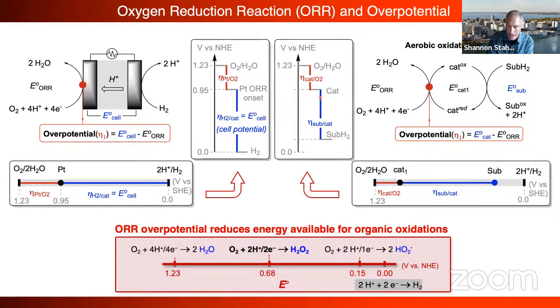In organic oxidation chemistry, it actually depends. And I hope the take-home message you take away is, at least conceptually, thinking about this overpotential for O2 reduction, overpotential for substrate oxidation. You may want a catalyst that sits down here very close to the substrate oxidation potential, so that you have a very exquisitely tuned catalyst with very good functional group compatibility. You may not want to hit it with a sledgehammer in this way, with the large driving force. And so sometimes you want to expand the inefficiency of O2 reduction so that your catalyst